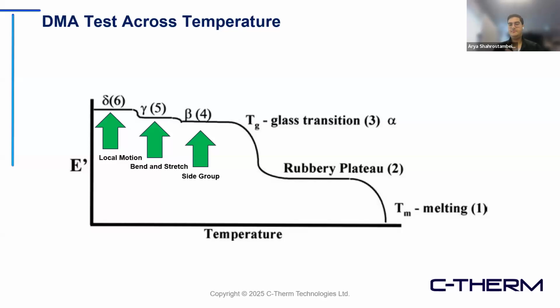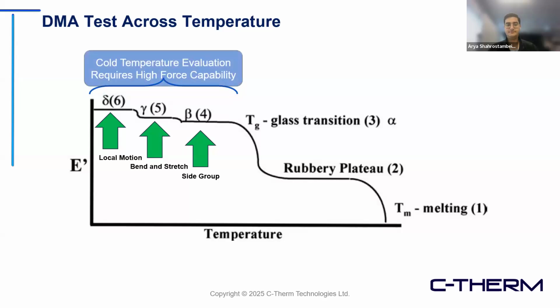So this makes DMA extremely useful for applications at lower temperatures, since at different stages, the brittleness can be different and the behavior of the material can be different. And this is the importance of DMA. And in the region that you can see with the blue brace, this is the stiff range of the material. And it's exactly the region that you need to have an instrument that is capable of deforming the sample within the range of stiffness.